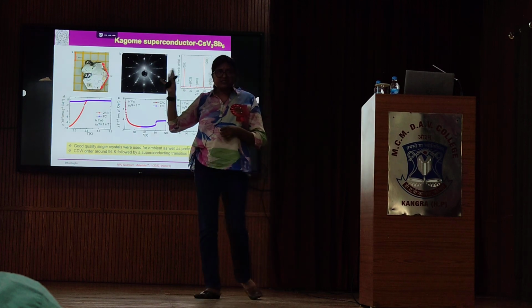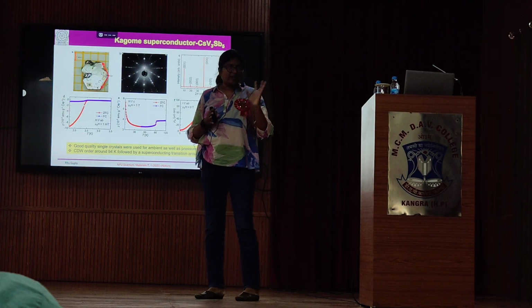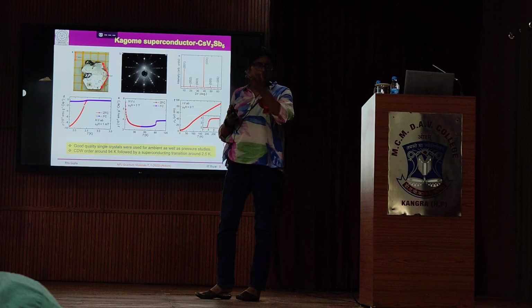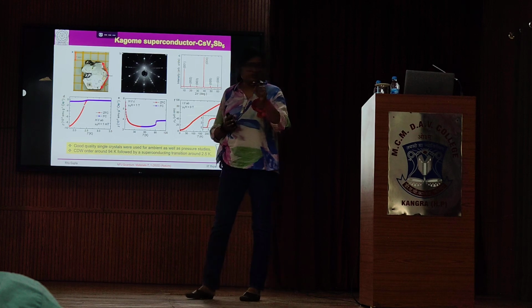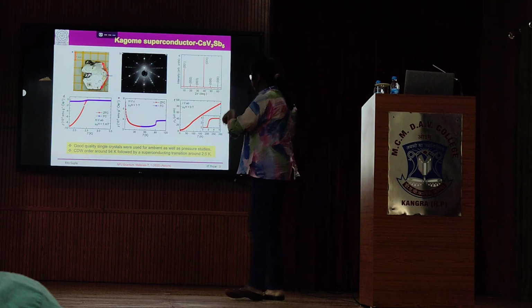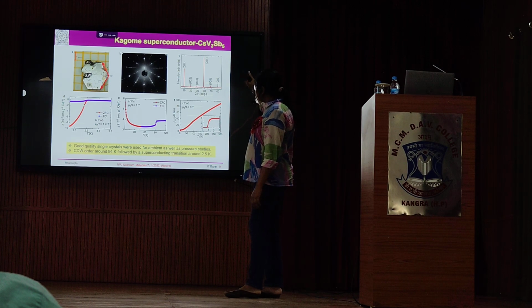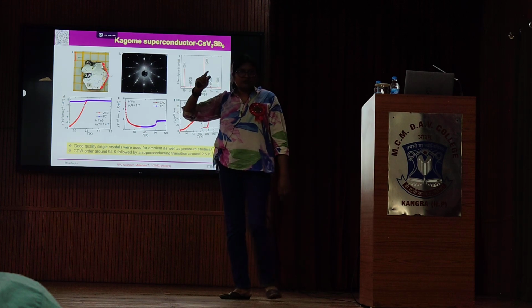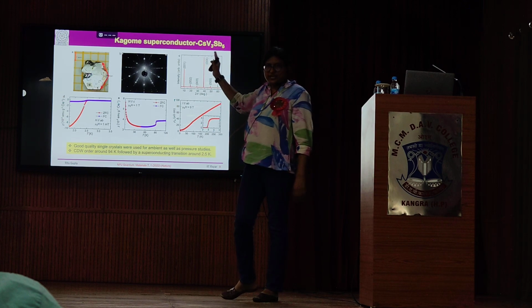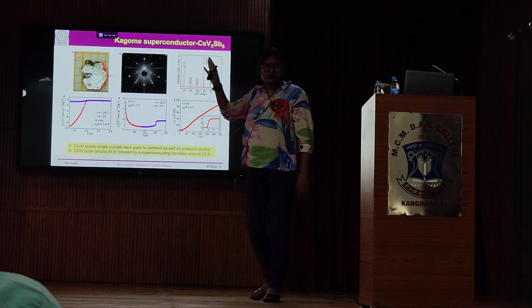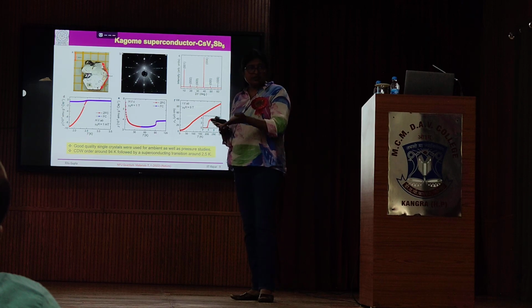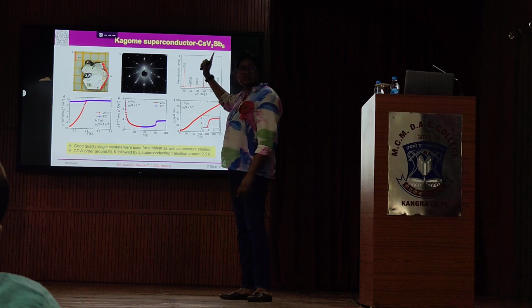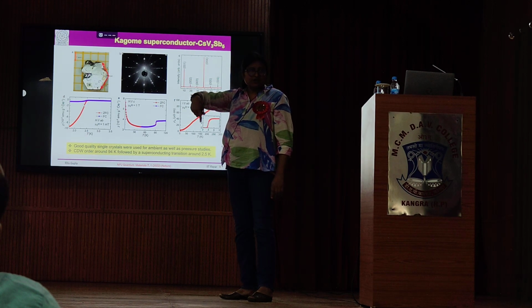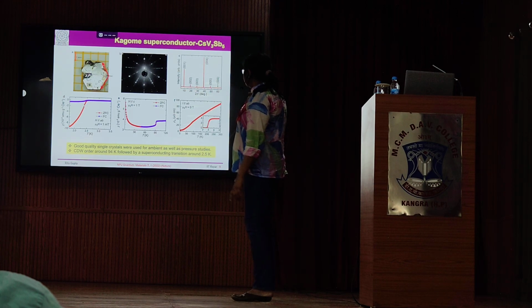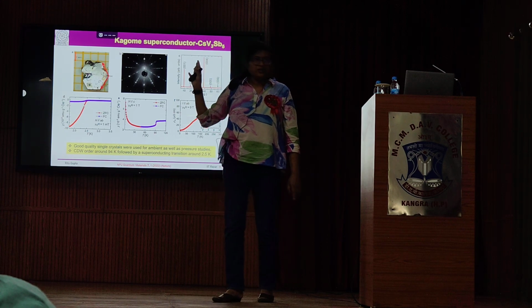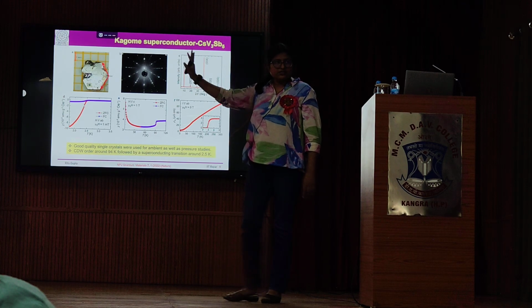Then the third picture is the XRD. So basically you all know, at least theoretically, how to perform X-ray diffraction, Bragg's law, right? Whenever the Bragg's condition is satisfied, you will have a peak in your spectrum. But here if you look at the peaks, these peaks are along 001, 002, 003. So these are not peaks like 110, 100. You are only getting certain peaks. So this is 00L planes you are getting. That means your crystal is oriented along the C-axis. The perpendicular to that crystal is the C-axis, and inside the plane is the AB plane. So this is what this XRD is telling you, and also you can see there is no additional peak, nothing, which shows that this crystal is very pure.